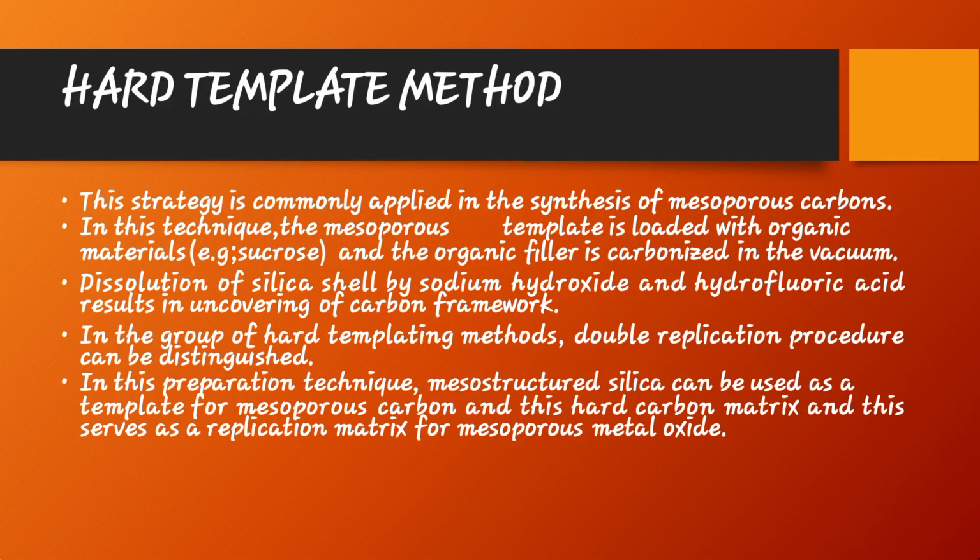Next, hard template method. This strategy is commonly applied in the synthesis of mesoporous carbons. In this technique, the mesoporous template is loaded with organic materials, for example, sucrose, and the organic filler is carbonized in the vacuum. Dissolution of silica shell by sodium hydroxide and hydrofluoric acid results in uncovering of carbon framework.